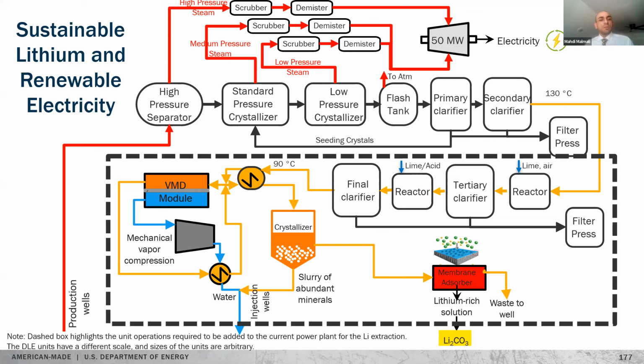And the water collected here goes to a mechanical vapor compression, which brings the vapor to superheat. So the brine is getting out of the membrane module. We can design it at any size, and everything is almost commercially available. Then it goes to a heat integration unit to take the heat out of the superheated vapor and bring it back to the brine again. So this way we will protect and preserve the heat inside this concentration loop. So this goes back and forth until we get to a concentration that we think it's ready for crystallization. And everything is going to be modeled and guided by thermodynamic models which we have in place.